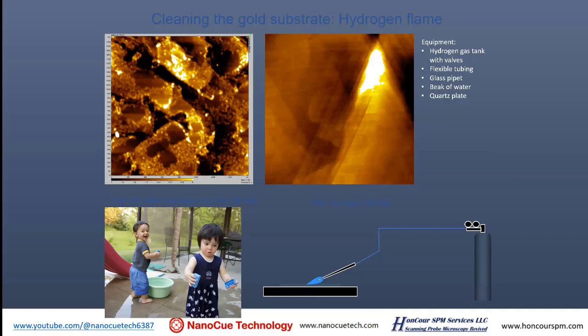So one easy way is to burn the surface with hydrogen flame. And this is actually very simple. You have a hydrogen tank, and then you have a glass pipe, and then you hook up a soft tube, and then just ignite the hydrogen and adjust the flame and sweep the surface. And then after a couple of sweeps, the surface is very, very clean. The one on the upper right corner was just being cleaned. Super, super clean. You can see atomic steps. A good way to clean anything is to burn it away.